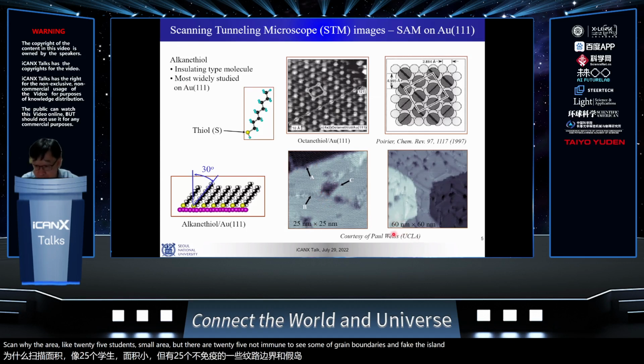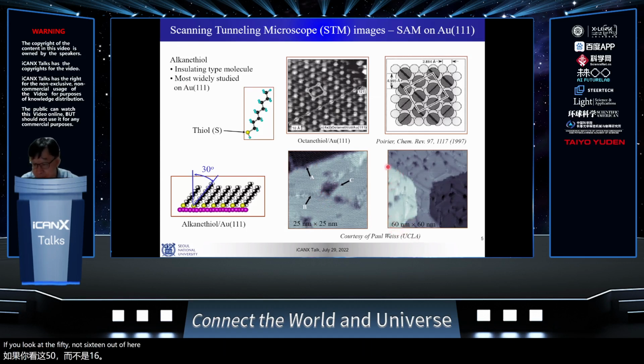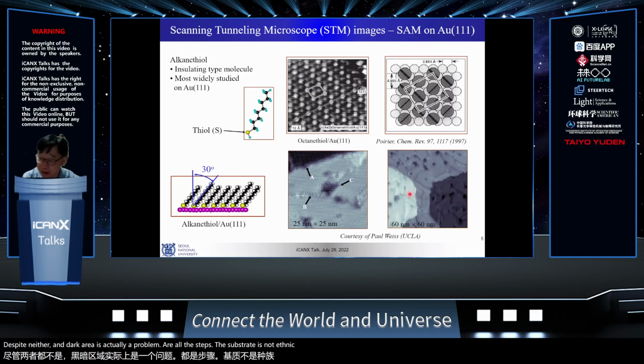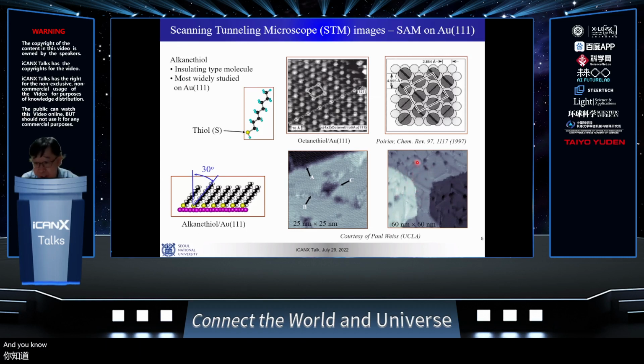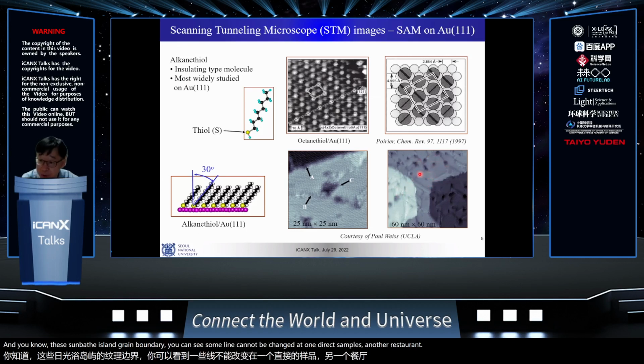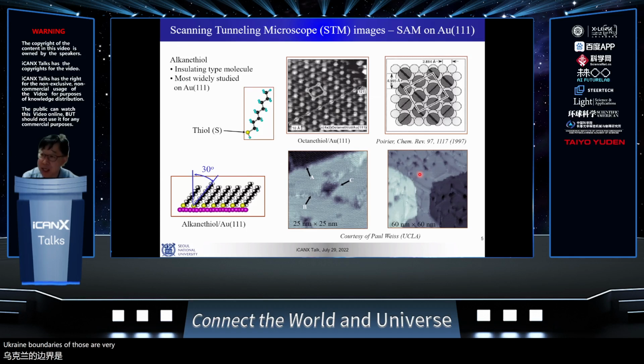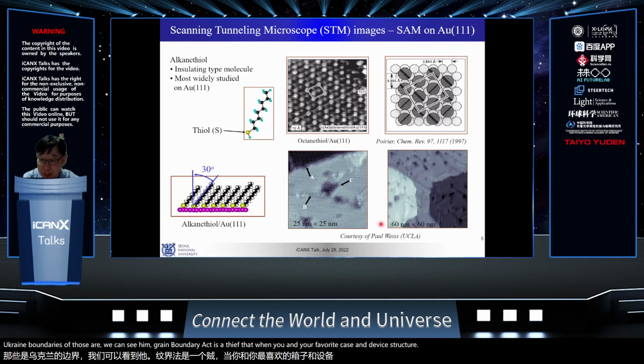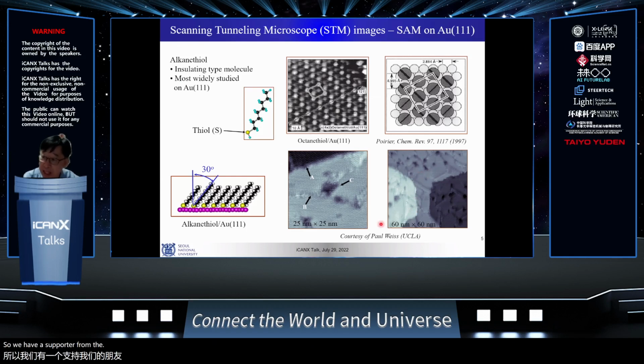If you look at 60 nanometers, you have this bright, middle, and dark area, which is actually from gold steps. The substrate is not atomically flat. And in addition, there are islands and grain boundaries. You can see some line patterns in one direction, and there's another direction of grain boundary. So those vacancies and grain boundaries act as defects when you fabricate some device structure. Okay, so we have some ordered structure, but it's not perfect.